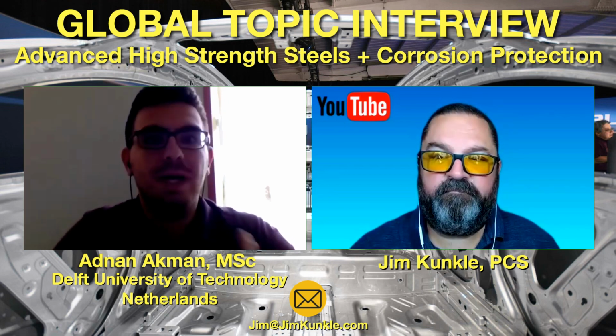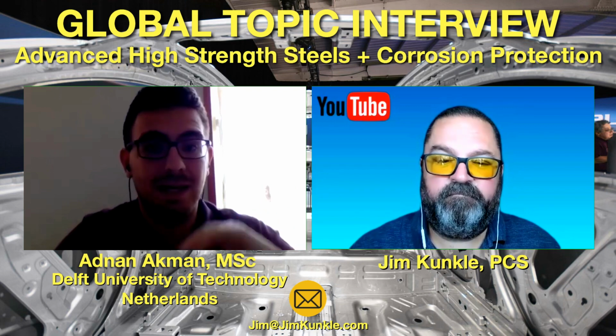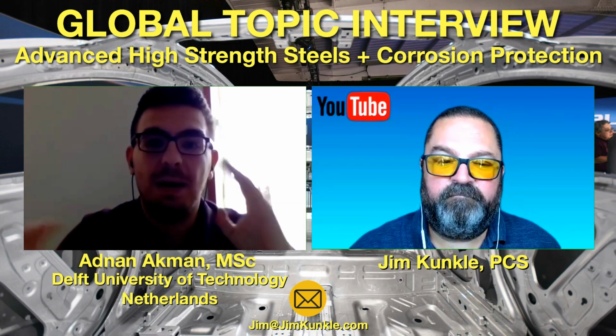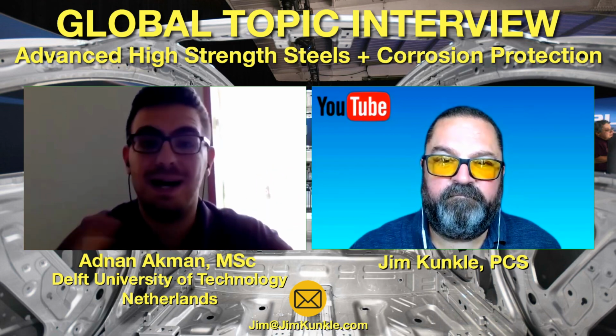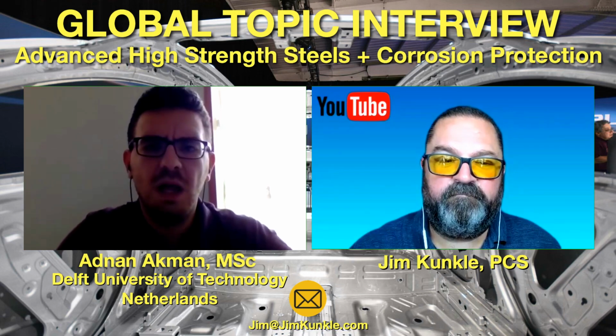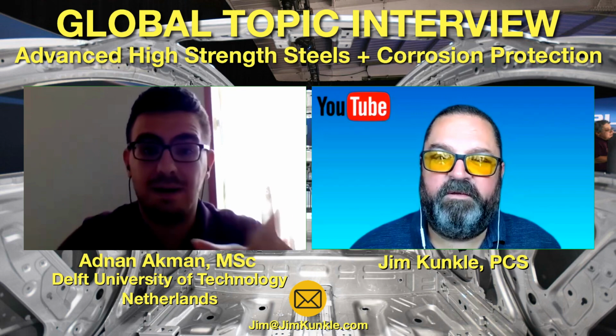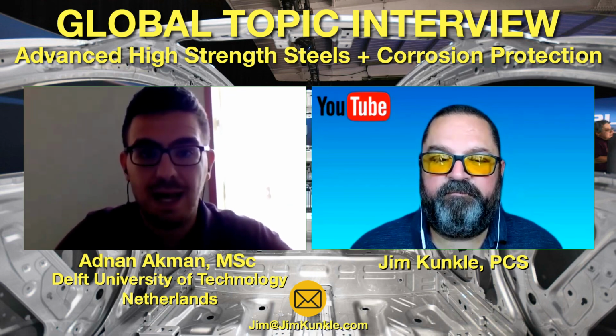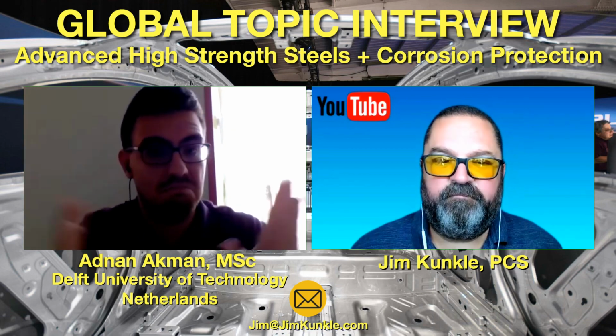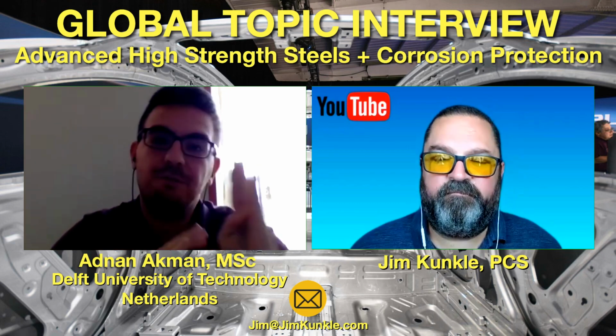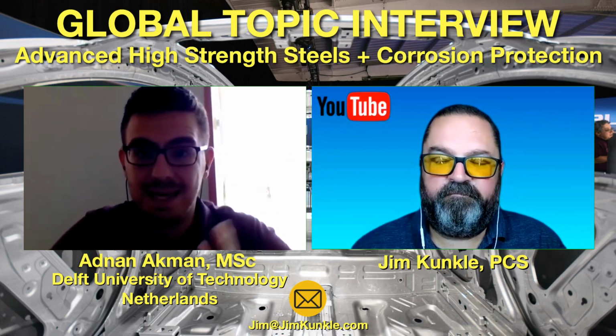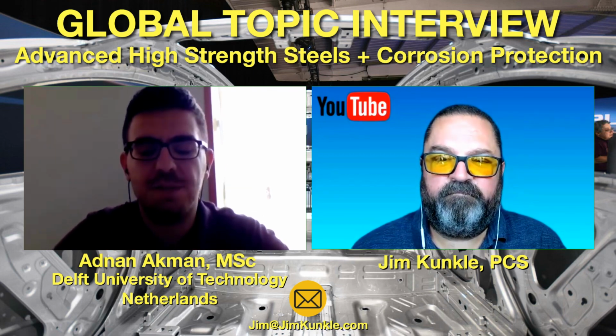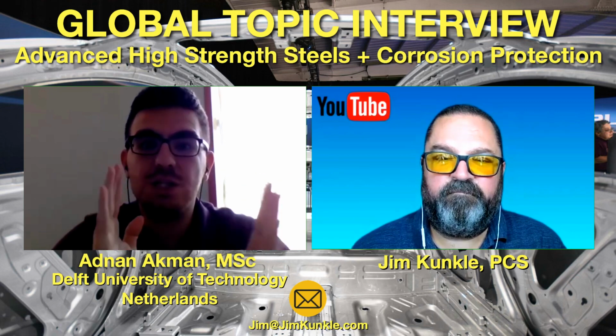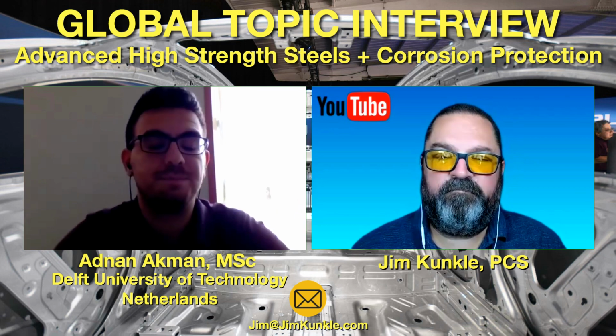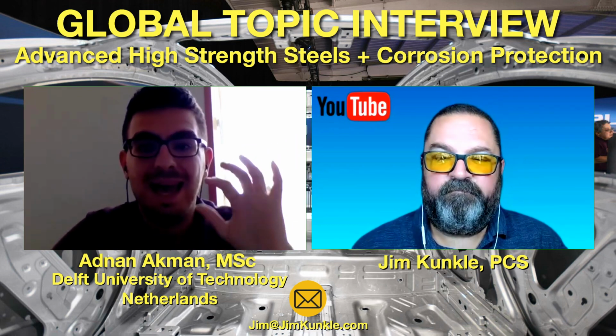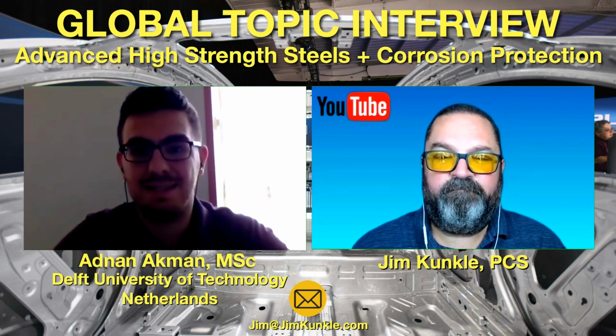So, for example, quenching and partitioning is a special heat treatment. I mentioned in my first talk, for example, the chemistry and heat treatment profile is different compared to other steels, high strength steels or low strength steels. So I mentioned lots of steel. Dual phase steels, TWIP steels, martensite steels. But what about an application in real life? So if you consider a car, in a crash zone, for example, or in a high-speed crash, the front and back side of the car called crumple zones in the case of crash, and the middle side of the car called safety cage. Safety cage is the location actually where passenger compartments are located. We are carrying passengers. So in a case of crash, crumple zones have to absorb energy as much as possible to protect the passengers.